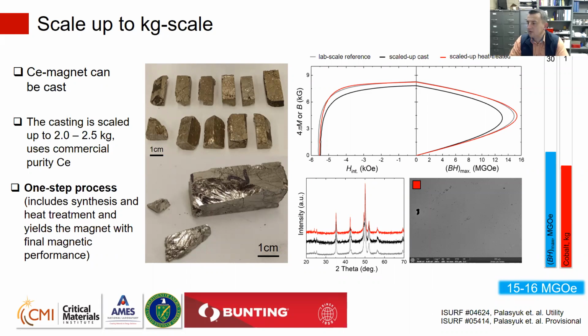Can you mill to get anisotropic powder and then use conventional techniques to consolidate? Probably not, because sintering was tried already in CMI, and if grains are small, it's very difficult to reach the performance which is reached through the casting. Maybe because if you have smaller grains, then you introduce all the powder problems or powder sintering problems associated. Can you mill it? Yeah, I think you can mill it, but again, consolidating the powder is difficult.